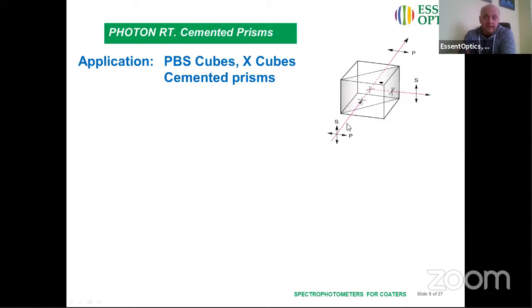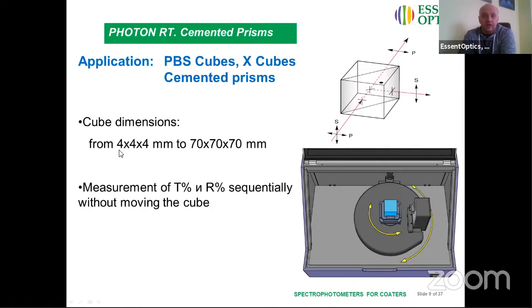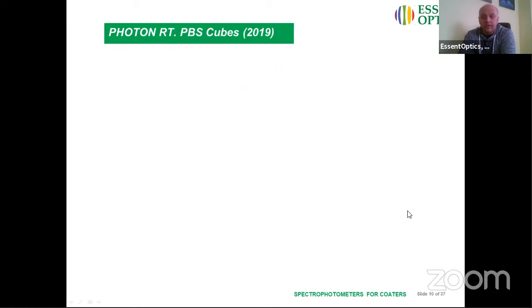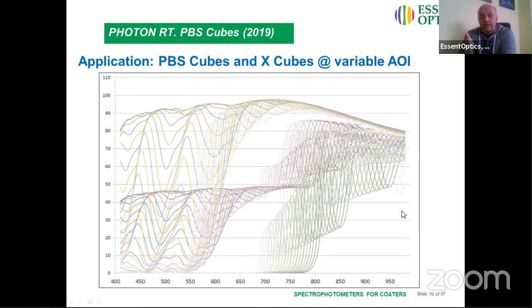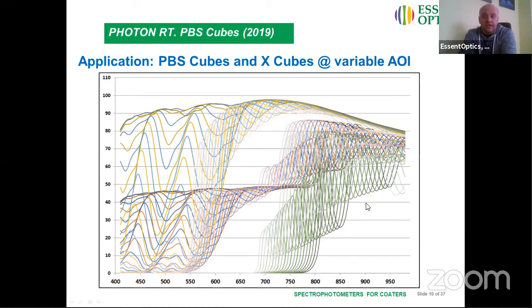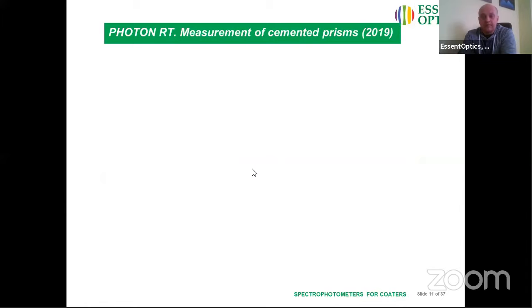So the cubes is a clear example. We can go from 4 millimeters cubes up to 70 millimeters cube in the same system, and can measure them clockwise and counterclockwise. But what's more important, and this is a particular application for AR devices, one of our customers asked us to measure these cubes at variable angles of incidence for he's producing goggles for AR applications. So that cube in that goggles was specifically measured at different angles of incidence, which we were able to do pretty well.